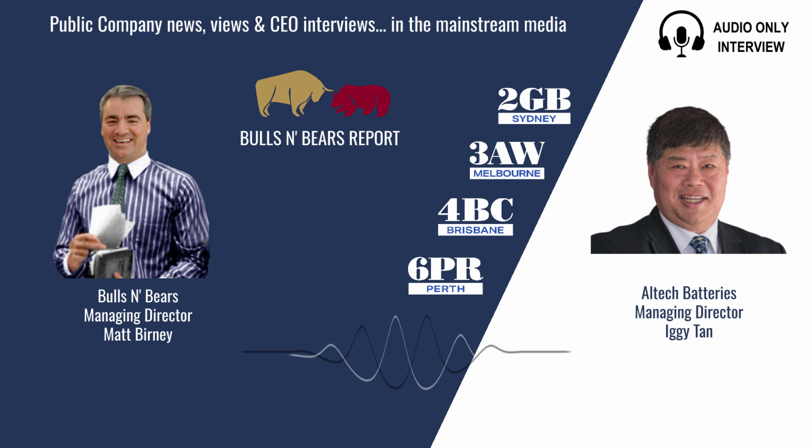Okay, Iggy, before we go any further, why do you want to put silicon into the anodes of lithium batteries and why hasn't it been done before? Silicon has 10 times the capacity to hold lithium, so it's a very promising anode, but the problem is that it expands 300% in volume and actually fractures.